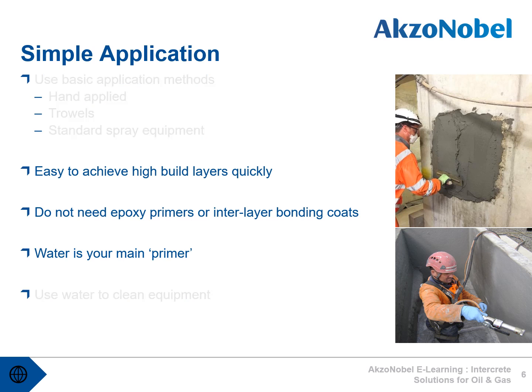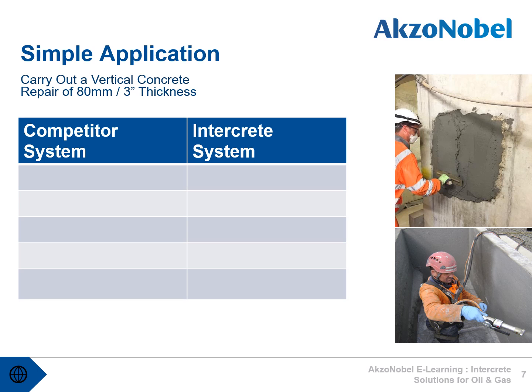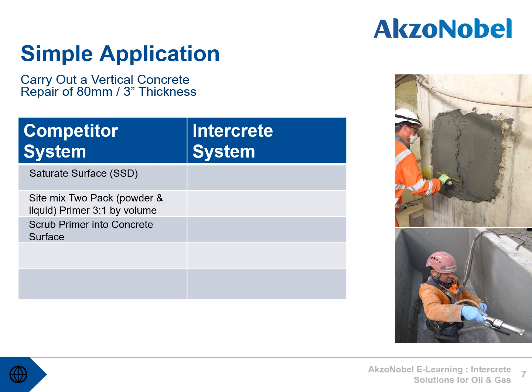As an example of the three points highlighted, we can compare the system of a competitor with Intercrete 4801, a high build structural repair mortar, on a simple vertical repair of 80 mm thickness. So for the competitor system, the first stage is to saturate the surface, get the concrete saturated with water, surface dry, so SSD. Then site mix a two-pack powder and liquid primer, 3:1 by volume. You then scrub the primer into the concrete surface. If the primer is allowed to dry, such as when working in hot countries, hot temperatures, that will need to be reprimed. And while still wet, apply a repair mortar to 80 mm thickness.